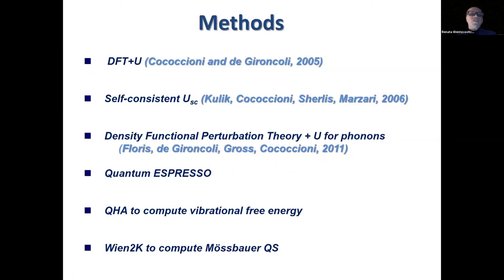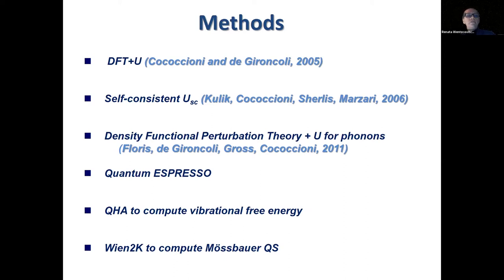The techniques we use for simulations are DFT+U, which I started studying early even before the method was published, and it was quite successful. Today DFT+U is done self-consistently and structurally consistent, and we do phonons with DFT+U. We use Quantum ESPRESSO, the quasi-harmonic approximation to compute vibrational free energy, and we use the WIEN2k all-electron code to compute Mössbauer quadrupole splitting, which is very important for understanding the spin crossover.